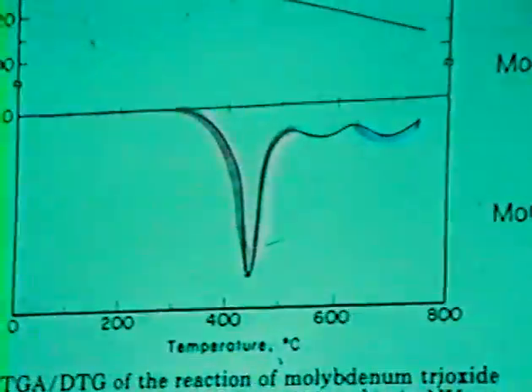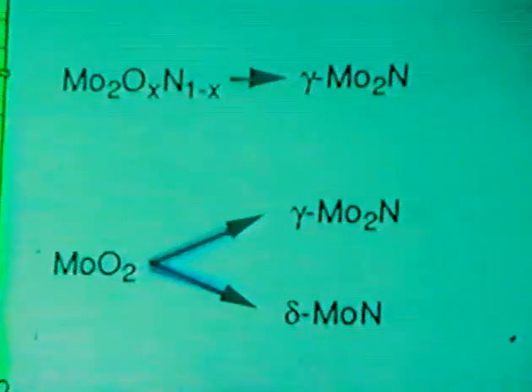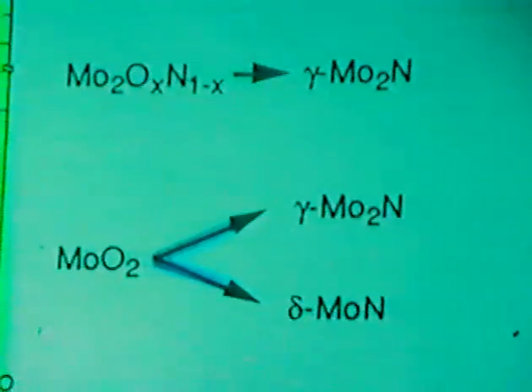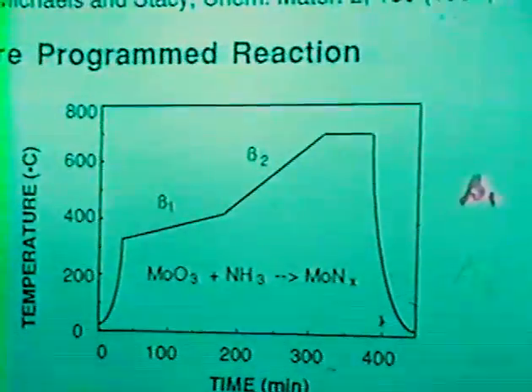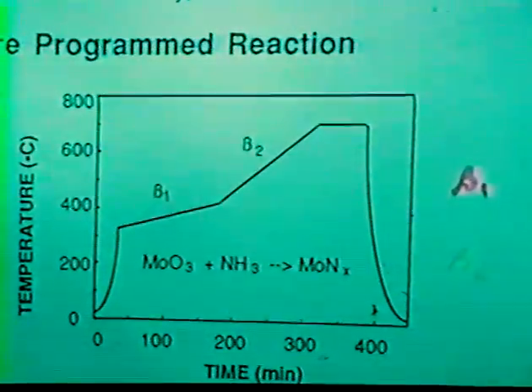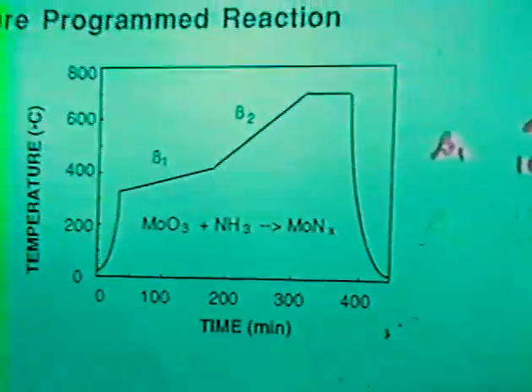When we started this research, we decided that we wanted to try and do rational synthesis of these materials, see if we can control the structural properties first, and then, if that was possible, see if we could control the catalytic properties. There was some work done by Jaggers et al., which suggested that there was a series of reactions through which moly trioxide is converted to either oxides or the nitride. And because these are parallel pathways, like other homogeneous reactions, we expected that the temperature at which the reaction is carried out, in addition to the heating rate that is used in converting the oxide into the nitride, would help us control the selectivity to product.